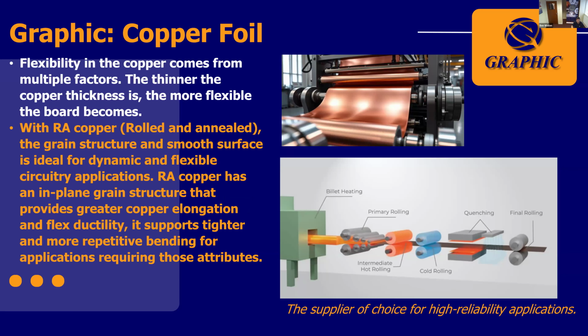Okay, so just to show you then how the rolled and annealed copper is produced. So this is produced by copper manufacturers, and as you can see, they are produced on rolls, and then the RA copper is applied to the polyimide films. So as I mentioned before, the rolled and annealed copper has a grain structure and a smooth surface, which is ideal for dynamic and flexible circuitry applications. So with that grain direction, you get extra flex ductility. It supports tighter and repetitive bends. And I will cover a little bit more of the benefits of the copper grain direction.